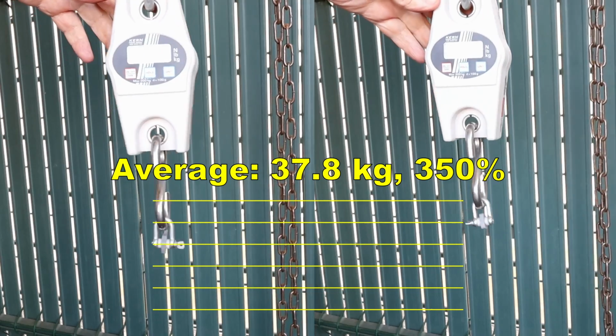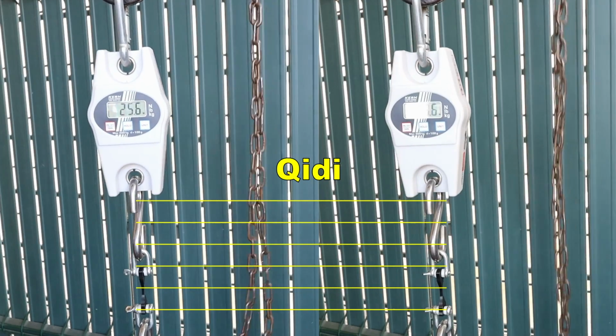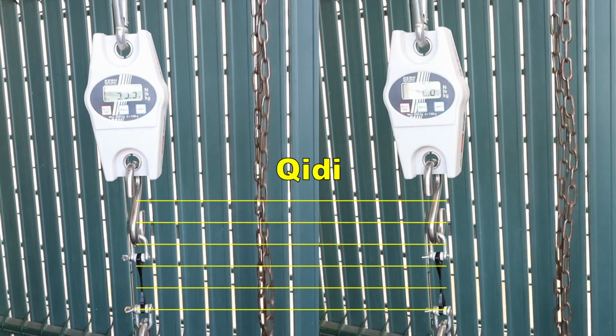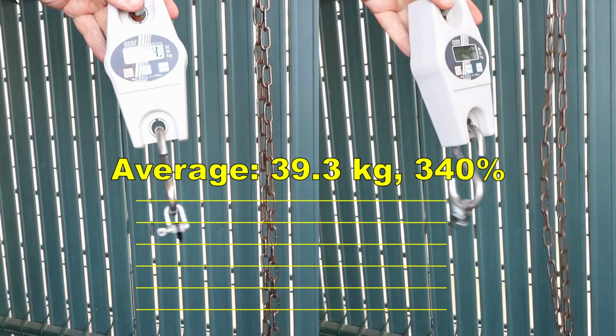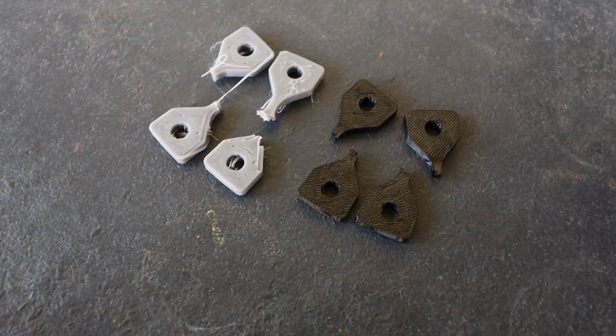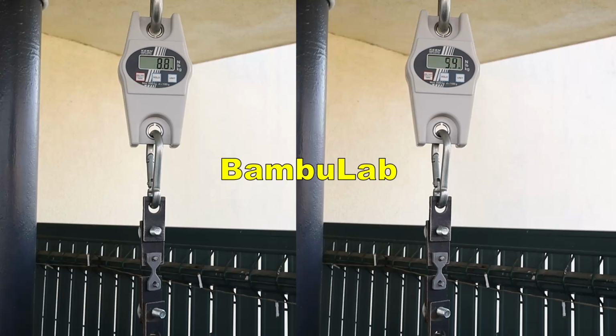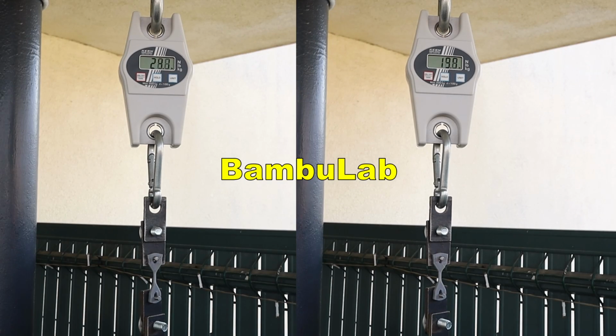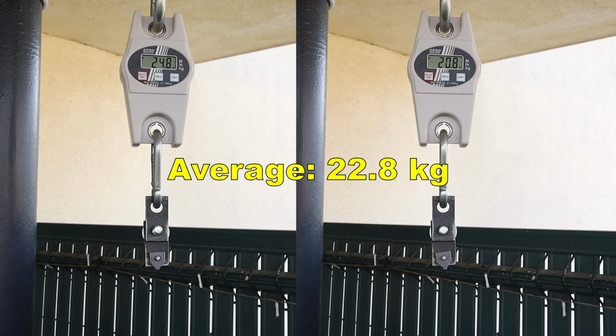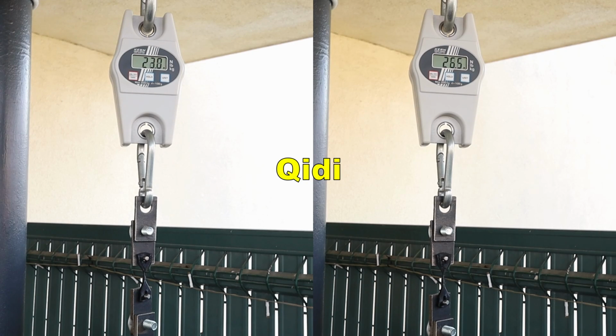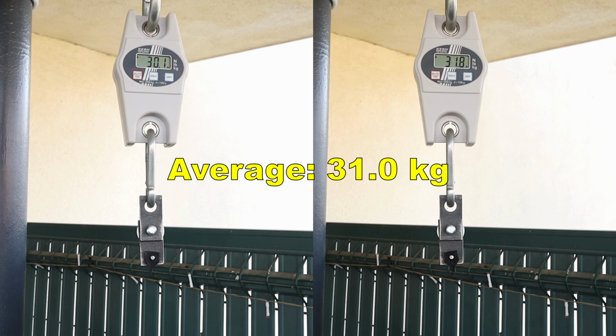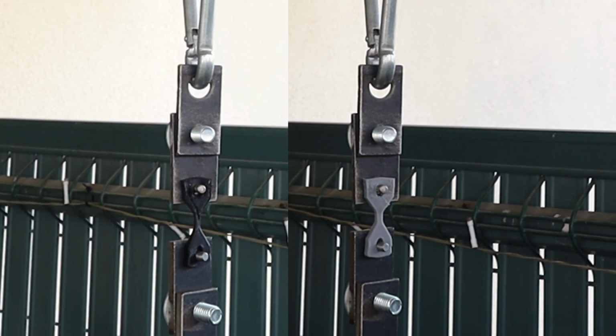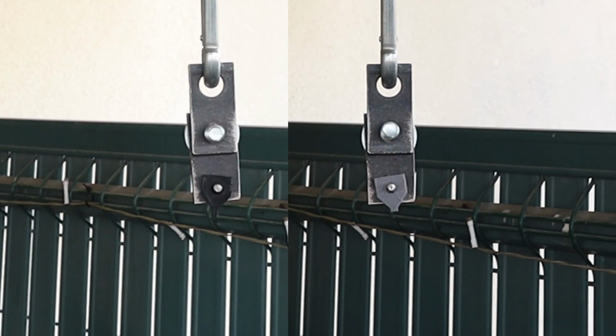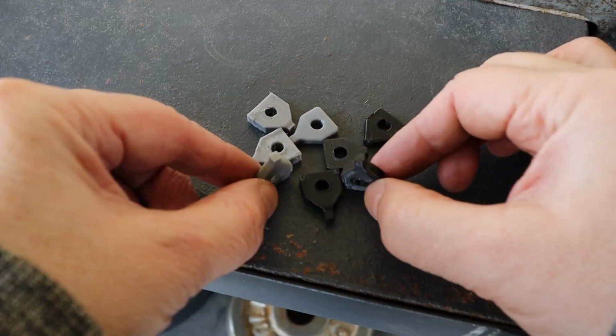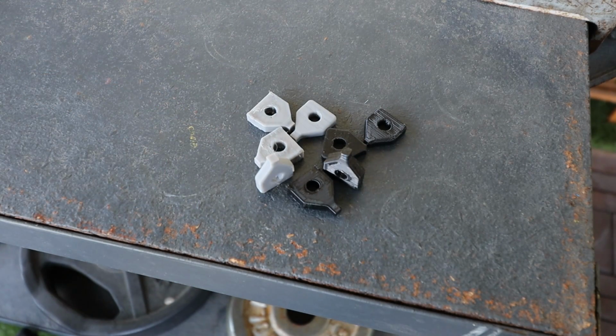The average break load is 37.8 kilograms, and this is now the Qidi filament. And very similar values I got here. And this is how they look, a very stringy break on the BambuLab filament. And now the layer adhesion test with the vertically printed objects, 22.8, which is acceptable for TPU filament, but Qidi was stronger, 31 kilograms. And here you can see side by side, very nice to see the prolongation too, not just the break. And this is how they look after this test.